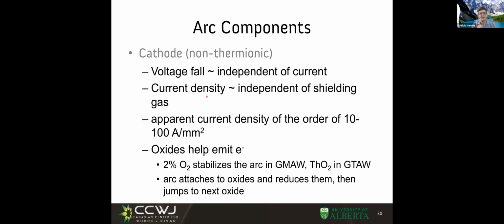The current density in the non-thermionic cathode is more or less independent of the shielding gas too. This is not the problem like we have in the anode. We change argon for CO2 and we change the current density very much in the anode. But in the cathode, no, it's more or less the same. In the non-thermionic cathode, the way the electrons come out is because of high localized electric fields.